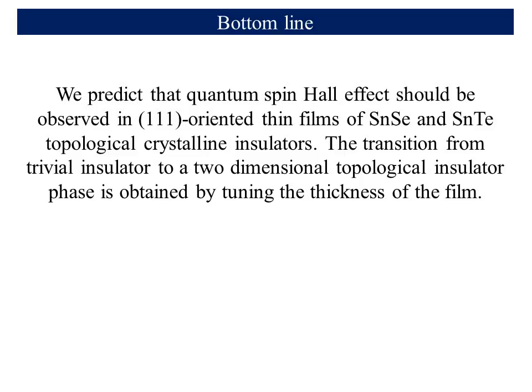We predict that the quantum spin Hall effect should be observed in 111-oriented thin films of tin telluride and tin selenide topological crystalline insulators. The transition from a trivial insulator to a two-dimensional topological insulator phase is obtained by tuning the thickness of the film.